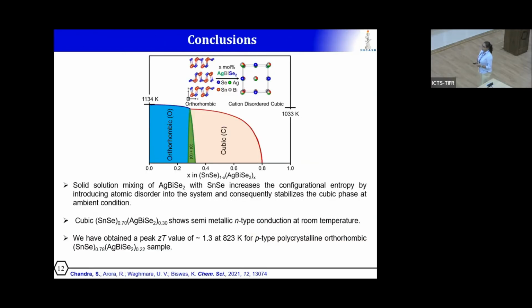So in conclusion, I was able to stabilize the cubic rock salt structure of SnSe with AgBiSe2 alloying. This cubic structure shows semi-metallic n-type conduction at room temperature. And we have obtained a peak ZT value of 1.3 at 823 Kelvin for the p-type polycrystalline orthorhombic sample.